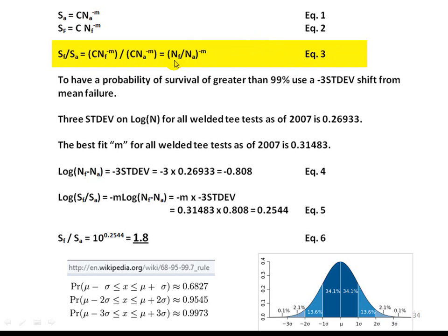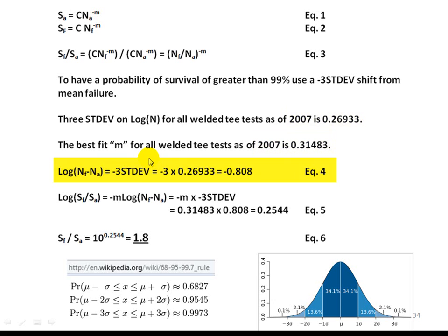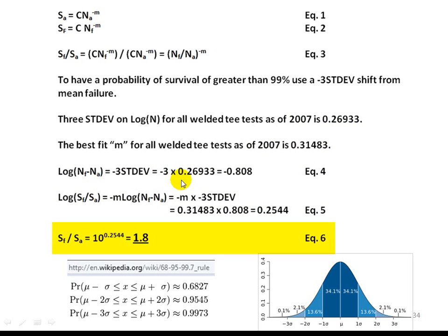The standard deviation based on log N of all welded test specimens collected by PRG in 2007 by Chris Hennant is a very reasonable value of 0.269. The best fit M from those same welded test data is 0.31483. So 3 times the standard deviation is calculated in equation 4, the log of equation 3 is given in equation 5, and the standard deviation of the log N from the data is inserted as the shift. And so from the log of the ratio of the stresses, the value of Sf over Sa from the test data using 3 standard deviations is 1.8.